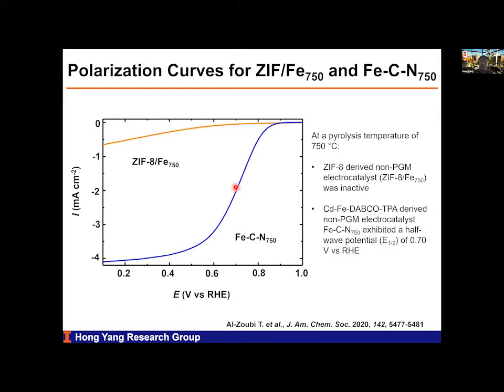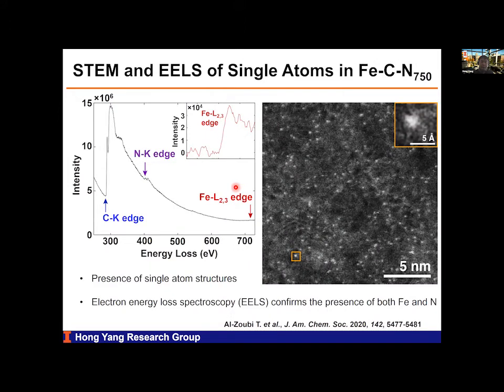But on further calculation, to see what the metal center could be, it should still contain, for example, the nitrogen species as well as the iron species, as demonstrated in this EELS study. And on the TEM image, you can see the single bright spots, and these are actually the single atoms of iron in the system.